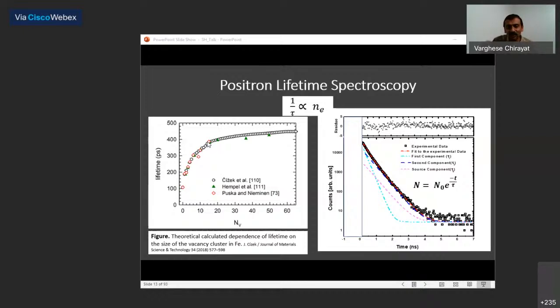Mainly, you can see, say, up to 10 to 15 vacancies. That means 10 to 15 vacancies together. It is not 10 to 15 vacancies apart. It's one big vacancy which is made by removing 10 iron atoms. Okay, so you can see up to that. You can clearly look at the numbers and predict what is the type of defect present in your material. Okay, so that is one piece of information that positron lifetime spectroscopy gives you. What is the type of defect present in your material?